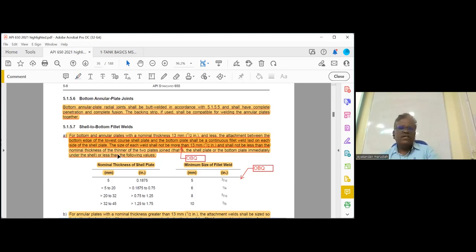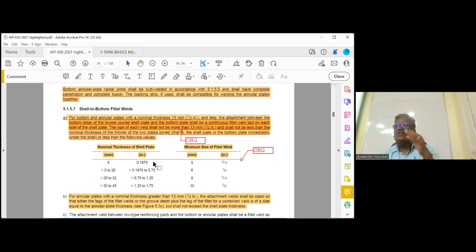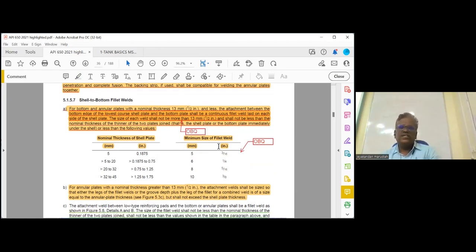I told you fillet weld size means leg length. Okay, and shall not be less than the thickness of the thinner of the two plates joined, that is shell plate or the bottom plate. Suppose half an inch, less than half an inch, maximum thickness allowed is half an inch. Suppose less than half an inch, what should be the size? For example, shell plate thickness and fillet weld size. Shell plate thickness 5 mm means it will be minimum 5 mm fillet weld size. 5 to 20 means 6 mm. 20 to 32 means 8 mm, 32 to 45, 10 mm. This is important, open book question.